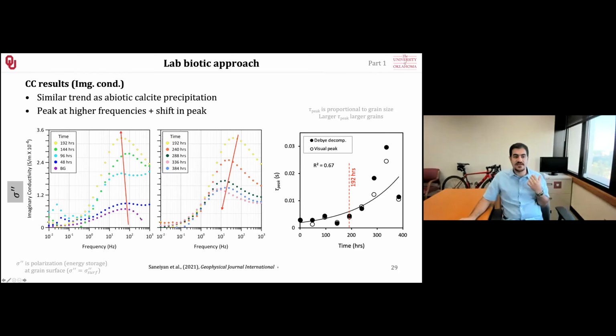So basically increasing, reaching a peak, decreasing, meaning that the calcite crystals firstly formed as a powder and were scattered all over. And then as we kept injecting food and calcium for these microbes, they basically produced larger calcite crystals that coagulated together and layered together. And that initial big surface area, because of the powder form, was reduced into chunks of calcite. So the magnitude of the signal was decreased.